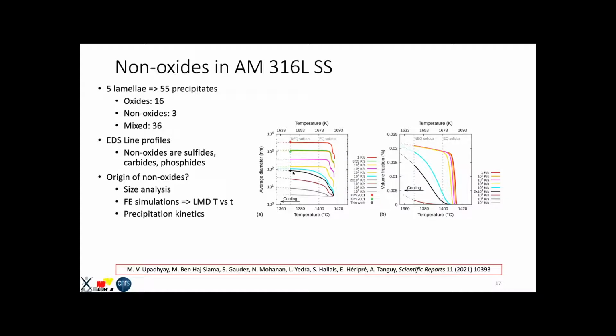We then started to perform simulations with the parameters that we fitted for different temperature rates. And we matched with 2 values that were given in the literature from experiments by Kim and co-workers. When we saw that the parameters were fitting very well, we said, okay, this validates our finite element simulations and the precipitation kinetics simulations. Then we looked at the volume fraction that could be forming at different temperature rates. The conclusion we drew is that non-oxides typically form at temperature rates less than 10⁵ Kelvin per second.